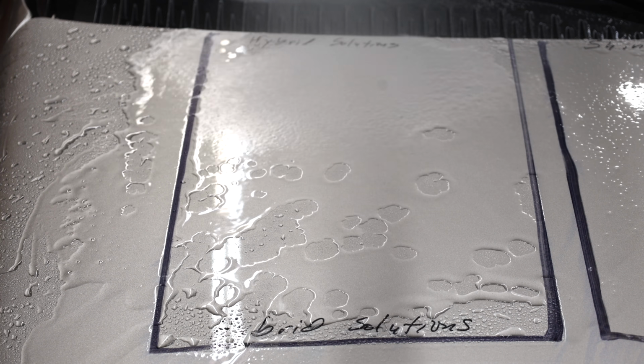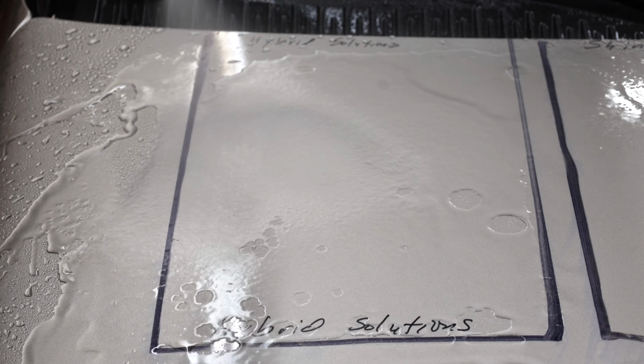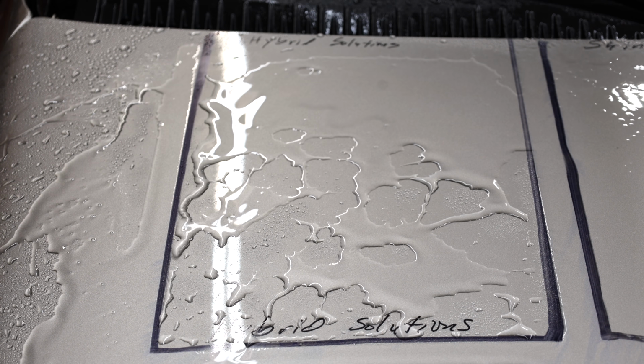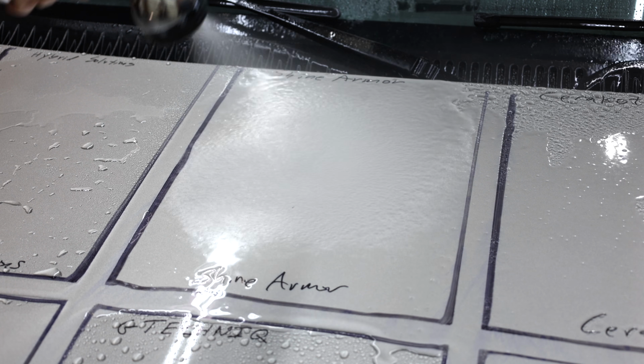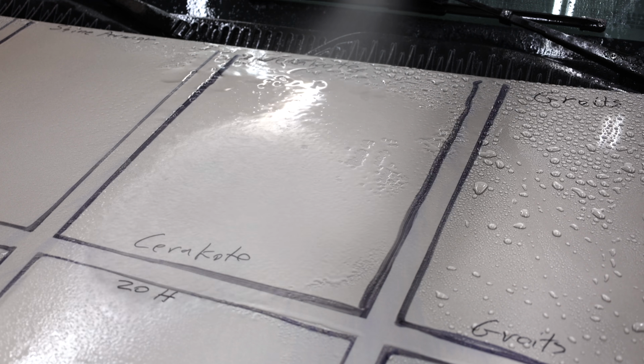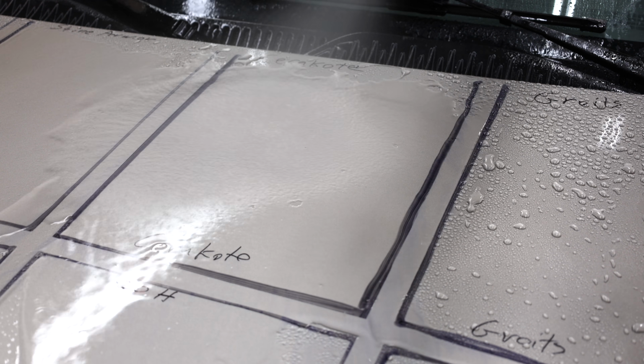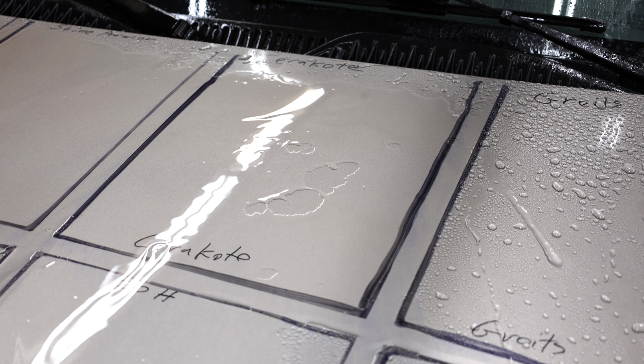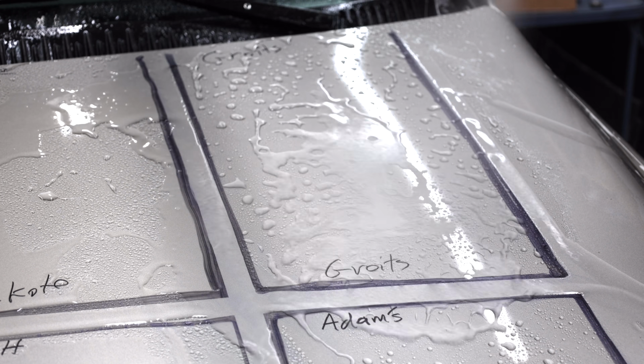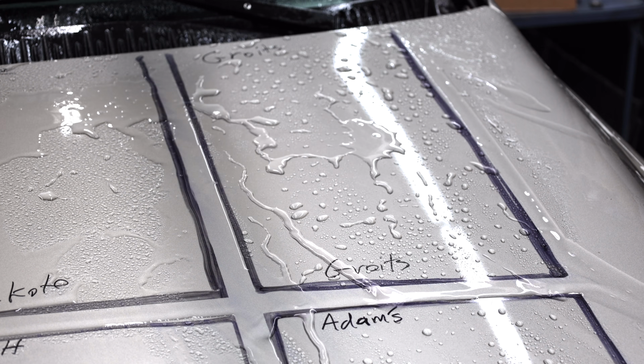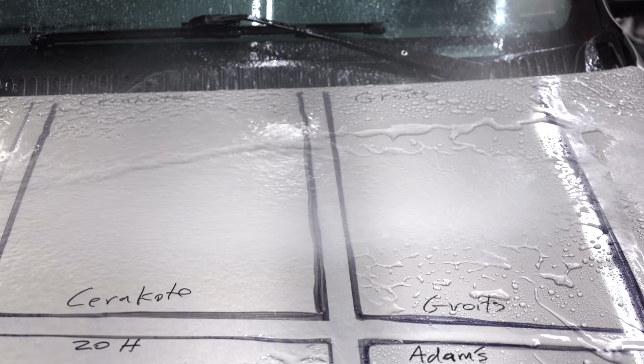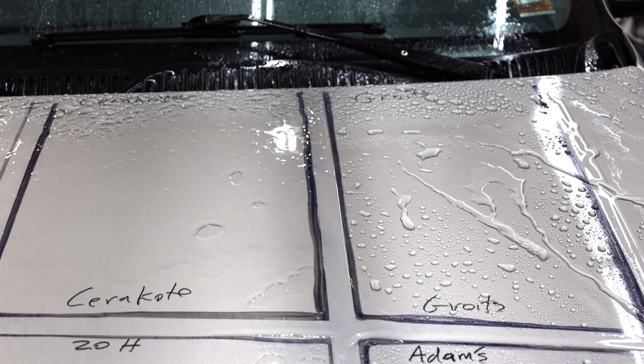The hybrid solutions continues to perform well for a budget coating, but the bug and tar remover caused quite a bit of damage to the hybrid solutions. Unfortunately, the shine armor is completely cooked. The bug and tar remover caused a lot of damage to the CERAKOTE, but is still providing some protection to the paint. The Griot is still ahead of the first three brands, and the water is still forming decent beads. Comparing the CERAKOTE to the Griot, the gap in performance continues to widen in favor of the Griot.